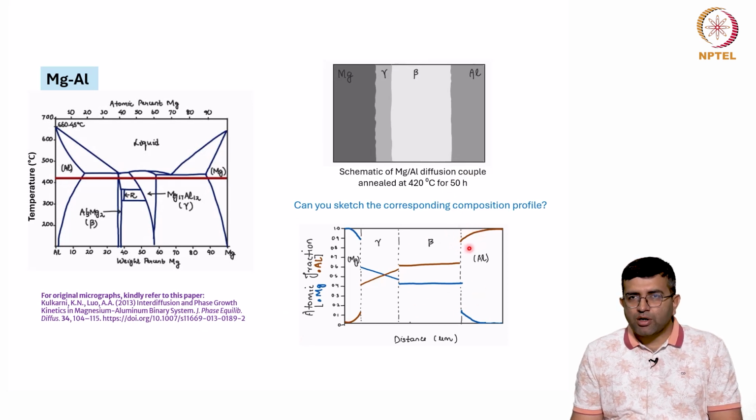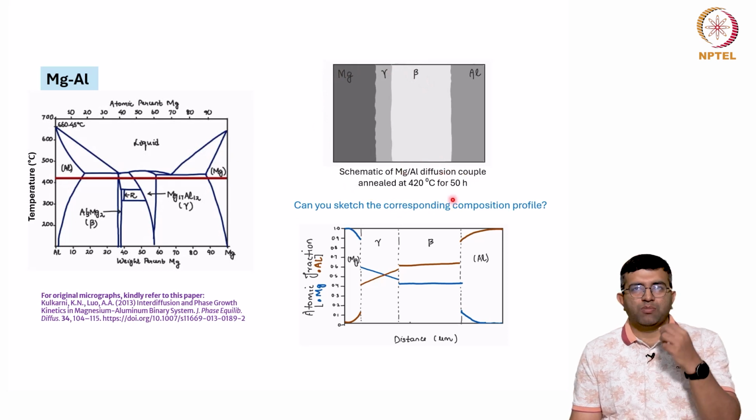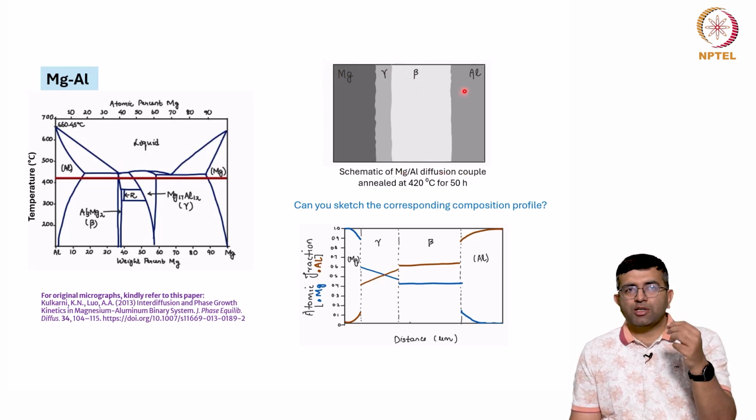The reason for such deviations can be, remember that this is an SEM micrograph which is reproduced here. Sometimes it may happen that the contrast of the solid solution, because the solid solution also has very close to aluminum composition, so it is aluminum where some magnesium is dissolved, may not be very clear.